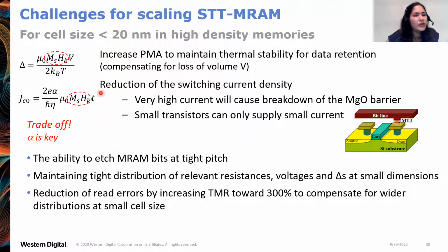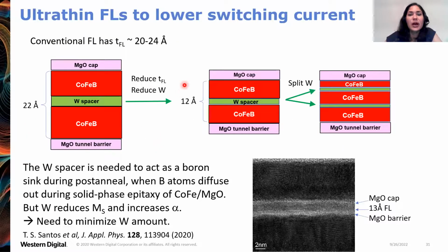So the first experiment I want to describe addresses this challenging trade-off between thermal stability and low switching current. Because if you're going to increase perpendicular magnetic anisotropy by increasing saturation magnetization and anisotropy field, that's also going to increase your switching current density. So for this reason, keeping the damping parameter low is critical. And so I'll describe our work to engineer the free layer to have low switching current.